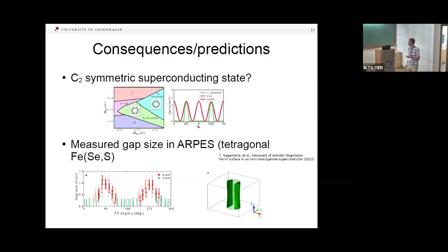Then I mentioned this C2 symmetric superconducting state, which we could stabilize with our two-band model with singlet and triplet pairing. And exactly this property, that at some angles you have a zero gap and then some finite gap with some C2 symmetry, was exactly measured also in the iron selenium sulfur system with an ARPES experiment. So here you see the gap seems zero, finite, and then zero in some angle regime. So in this regime, no pullback of the spectral function as a function of lowering the temperature below Tc is seen.